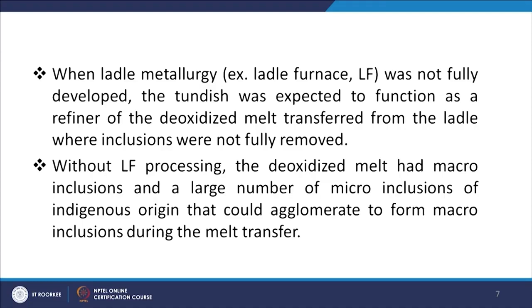Without the ladle furnace processing, the deoxidized melt had macro inclusions and a large number of micro inclusions of indigenous origin which will be formed inside, and that can agglomerate. So it also happens that you have many small indigenous inclusions, and they have the tendency to agglomerate and segregate, and they will be forming the macro inclusions during that melt transfer. That will be further detrimental, because they will try to go into the melt, and they will decrease the quality of the product.